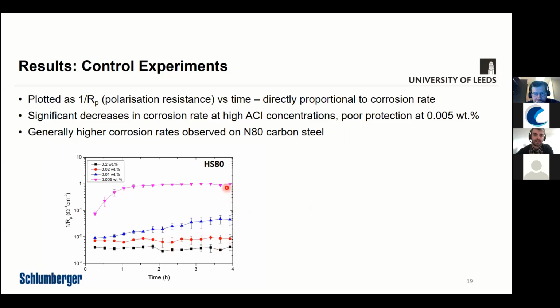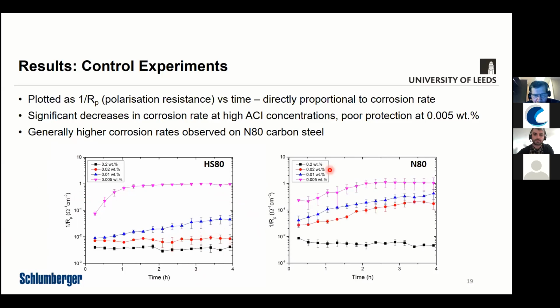But as you can see, and as you might expect, as you increase the inhibitor concentration, the corrosion rate, 1 over RP, decreases, and it becomes more efficient. For N80, similarly, increasing concentration was more effective. But generally, the corrosion rates are quite a bit higher on N80 due to the microstructural differences between the two steels. So what that told us was that the critical component in this is the N80 carbon steel. That's going to suffer more corrosion. The inhibitor concentrations aren't as effective. Therefore, this is the critical component for evaluating the staged approach.